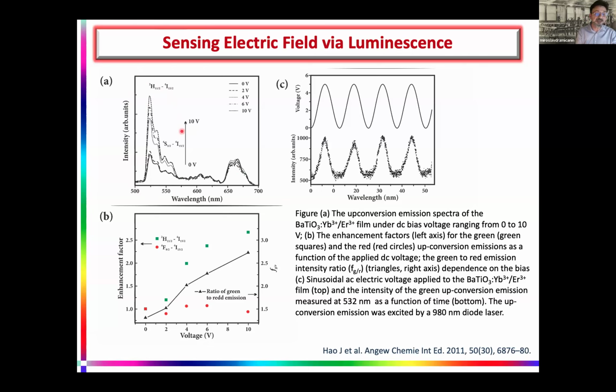And this change in the environment around erbium in ferroelectric materials changes this ratio. As you can see here, this is the dependence of the red to green ratio on the voltage that is applied to the material. And then here is an example. You have this sinusoidal modulation, and this is the optical response. It's perfectly matched. So generally, this is a very good concept if you want to remotely measure electric field by optical means.